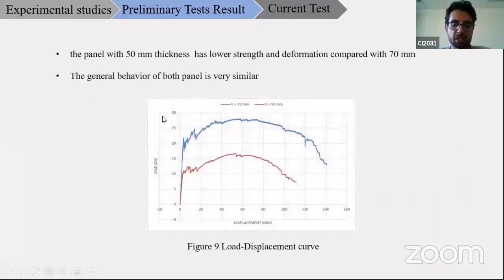Here, as we see, the maximum strength achieved in both panels occurred long after the initial cracks, and displayed a very ductile behavior. If these panels without traditional reinforcement were not having steel fiber, they are expected to collapse with the first crack, as here. So as mentioned before, the trial study aim was to define the thinnest possible panel without losing its strength and behavior. So it was decided that the 50 millimeter thickness specimen would be appropriate to choose for the final test.